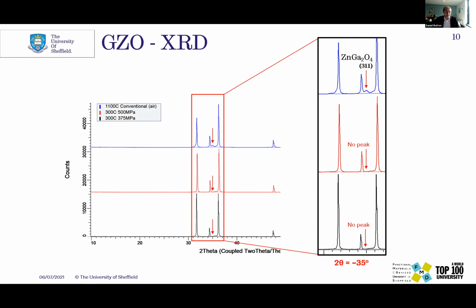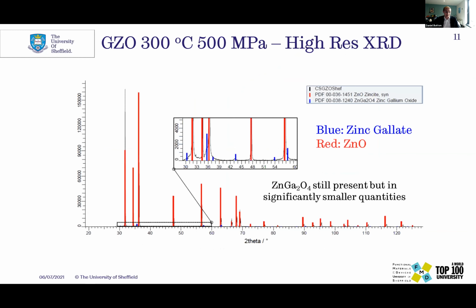Now, our general consensus is no, it's not generally good to have a random secondary phase appearing in your material, but regardless, it didn't seem to form in the cold sintered material. However, we did double check with some high resolution XRD. JM very nicely did that for me. And it did show that in the cold sintered, there was a very, very small amount of this gallate phase.